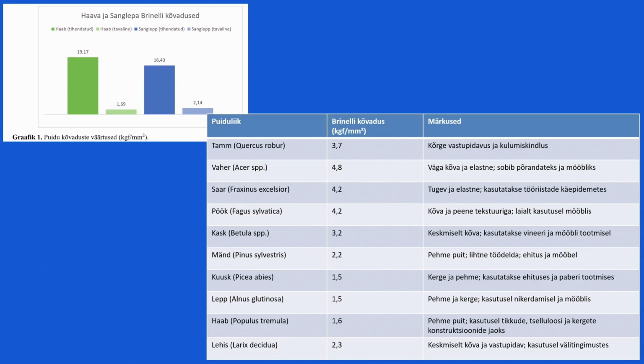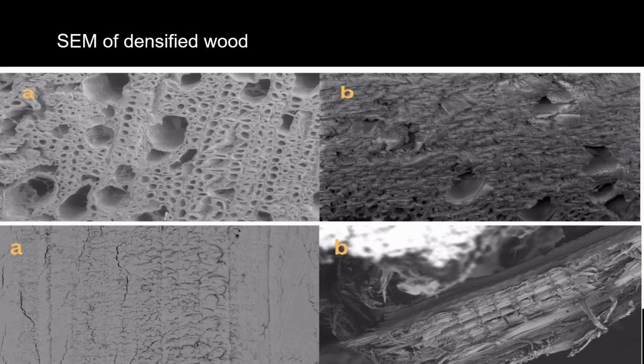For example, here we have oak, which is around, like we have 4 here, which is more than twice harder than aspen in its usual form. But if you look at the densified aspen, then the densified aspen is around almost 5 times as hard. So the densification makes the material quite much stronger.